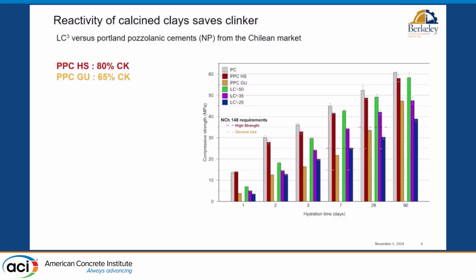And we took the two grades of commercial cement. These are not cements that we blend in the lab, but actually commercial products, with 80% clinker factor for high strength and 65% clinker factor for general use. And we compared them with LC3 type formulations. And what we did was to vary the clinker content to try to match the requirements of the standard in Chile with something that contains calcined clay.